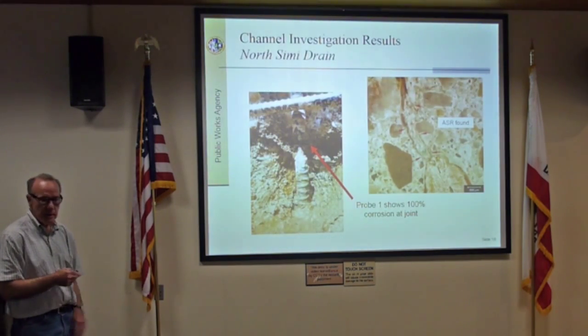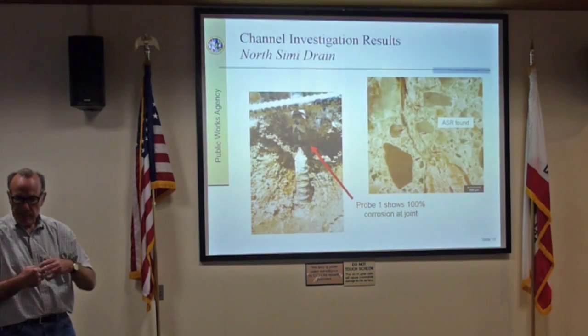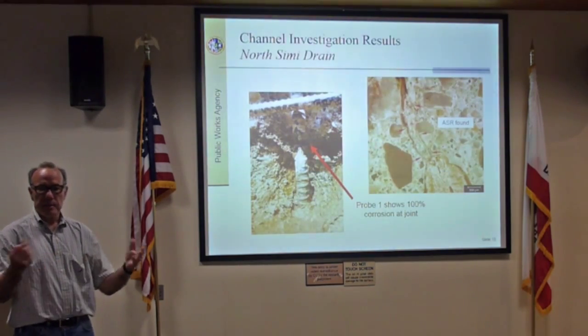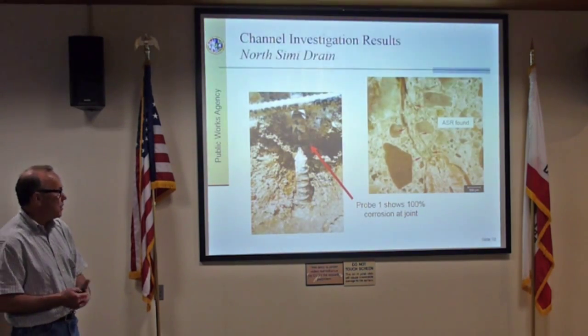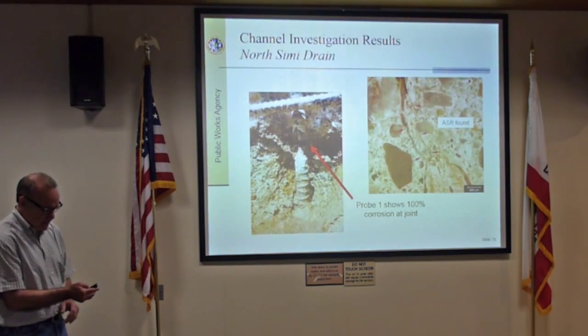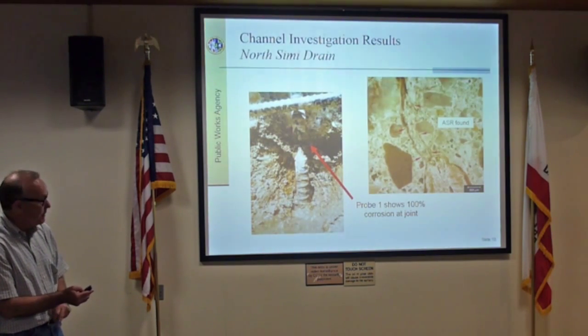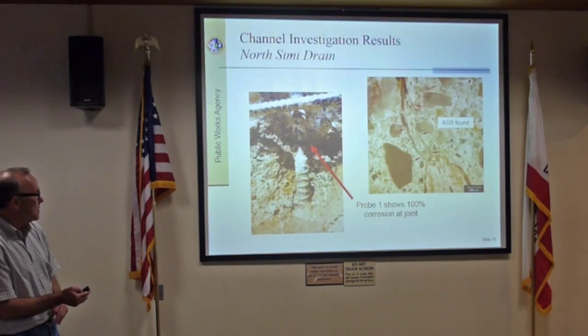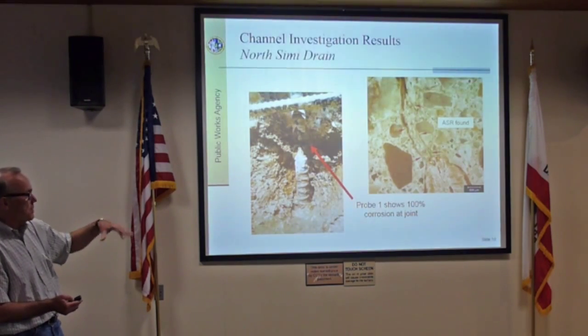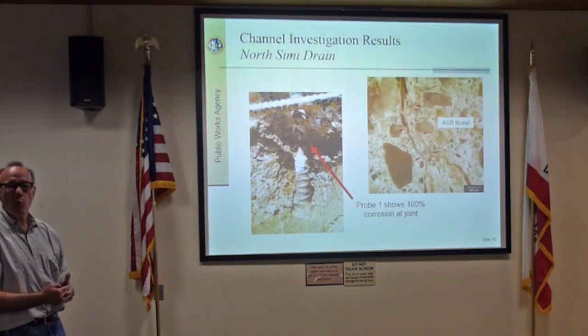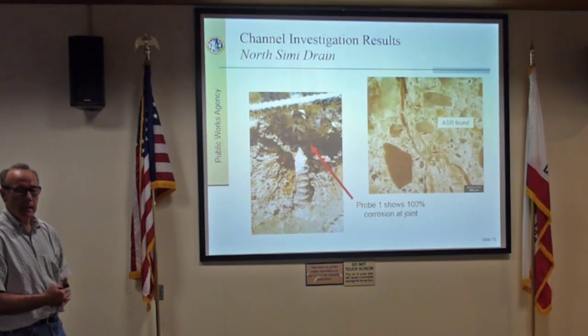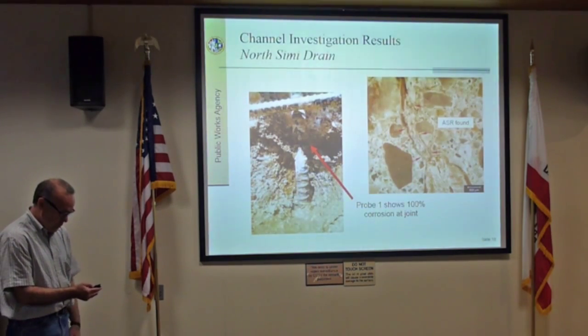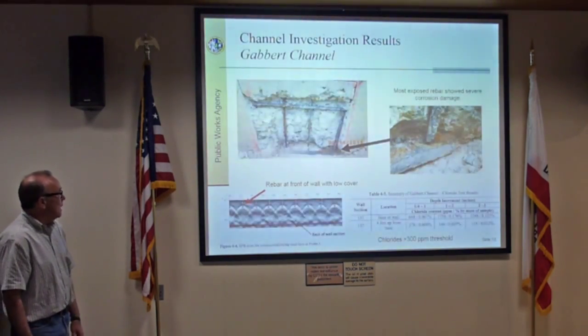There was some ASR that was detected in there, but that forms an internal cracking mechanism. There's this area in California, there can be a lot of incidents of ASR because of reactive aggregates. So that just adds to the process of where you might get some more permeability or cracking, allowing access to both water and oxygen.